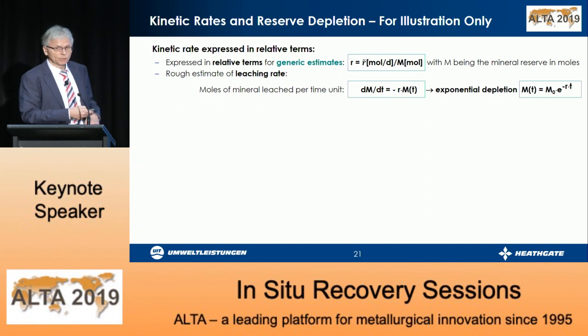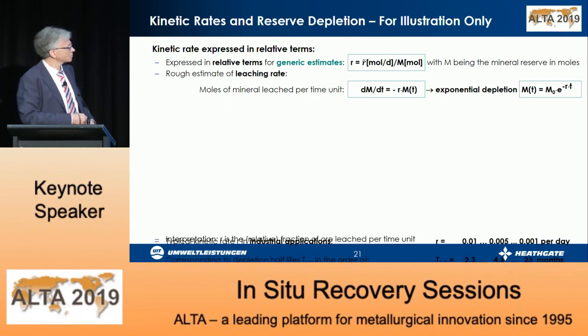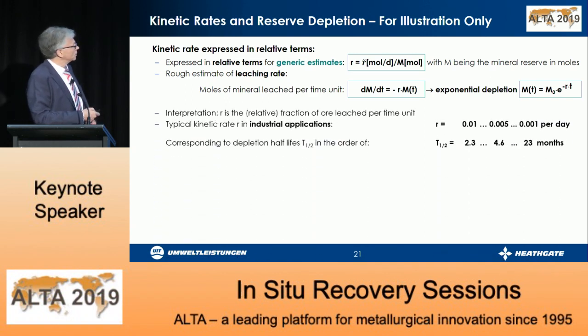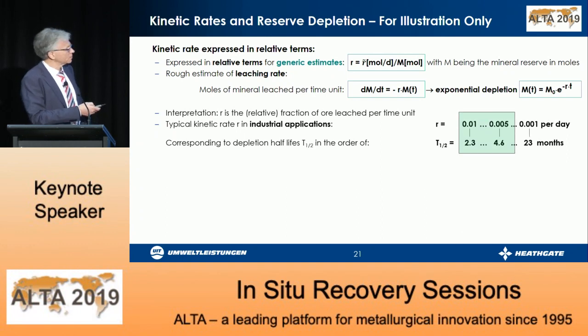So what we observe mainly is an exponential depletion of the reserve in the underground. So the overall rate that we realize in the industrial practice is shown here. That means the rate is in the order of 0.01 down to 0.005 and further to 0.001 per day. That's about the applicability range, corresponding to a depletion half-life of 2.3 to 4.6 months and 23 months in the last case. So what we prefer is to stay in this green area.